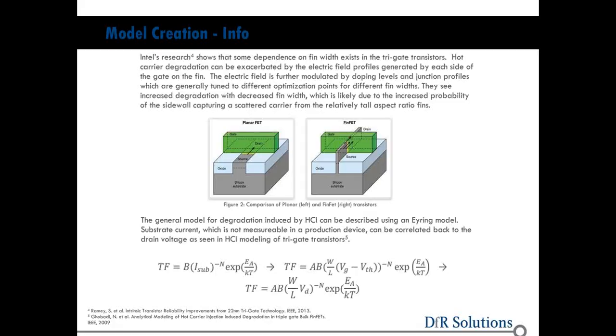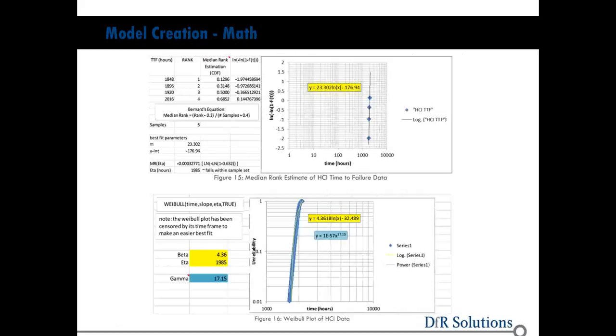Okay, so for this we tracked threshold voltage and core voltage of the CPU at about 30-second intervals for 4 to 9 months. At about 11 weeks we actually had cascading failures for the parts running at cold temperature. Here's some of that data. We can use time to failure data and some median rank estimations to come up with our beta value for Weibull, our characteristic life or eta, and also our power coefficient gamma, which would be the best fit line's exponential function, the x to whatever power, that gamma.